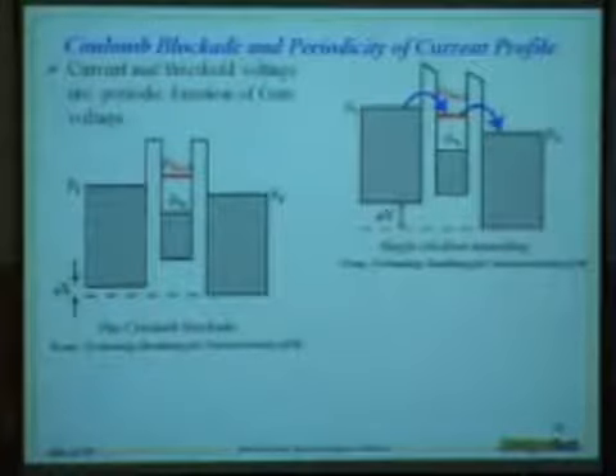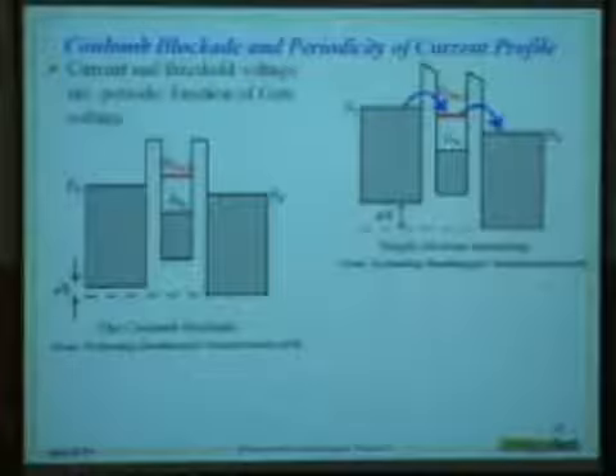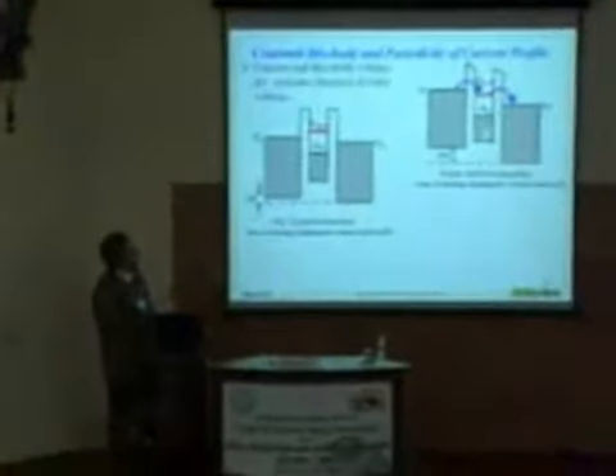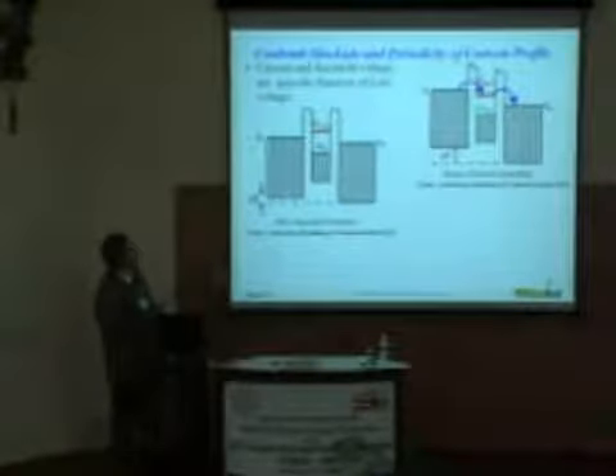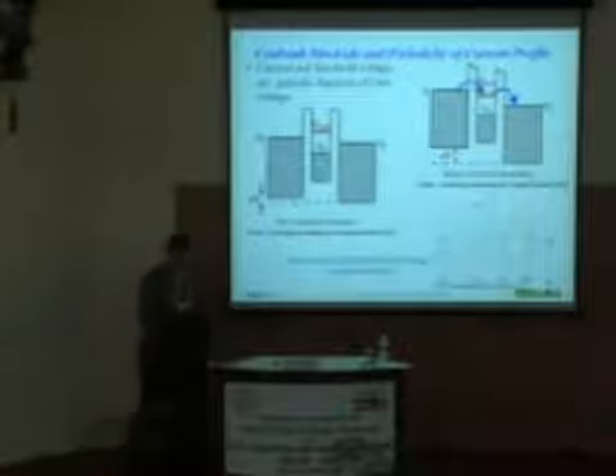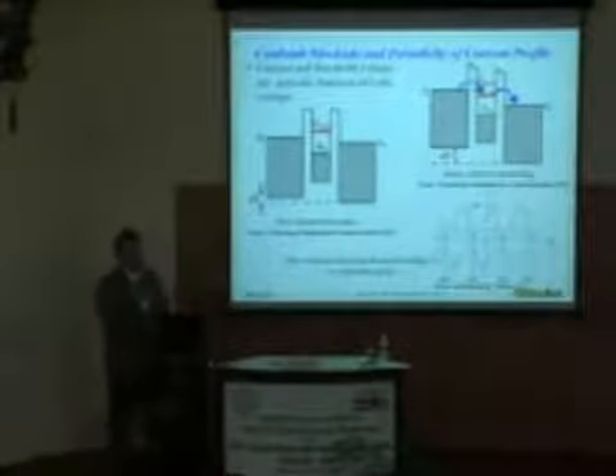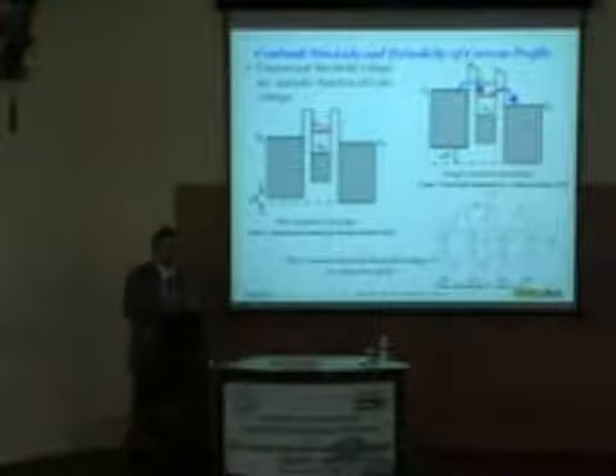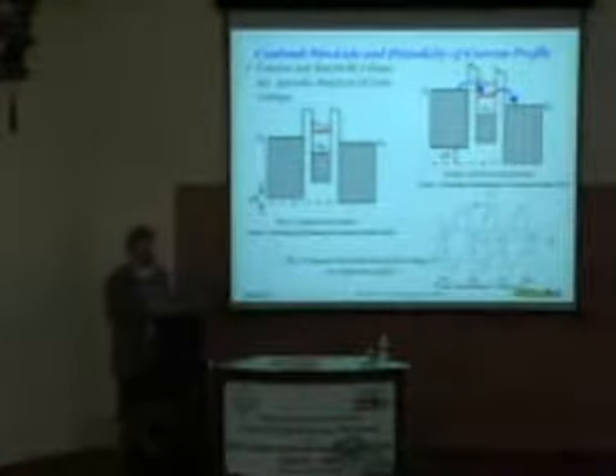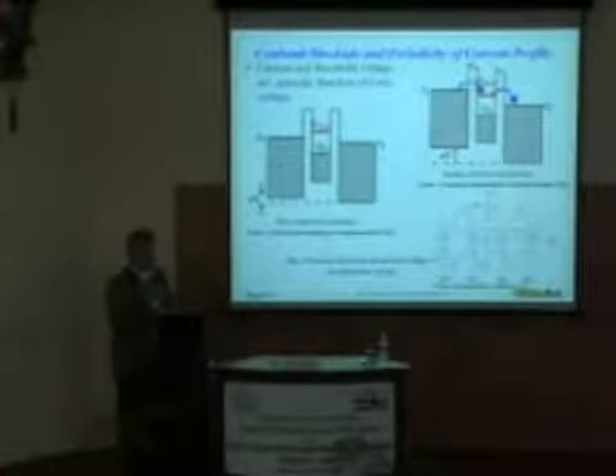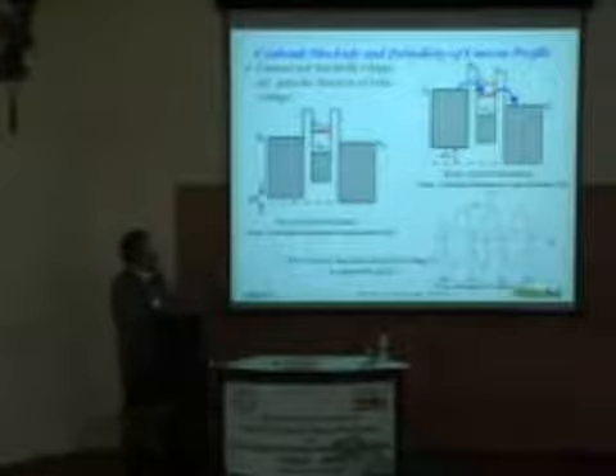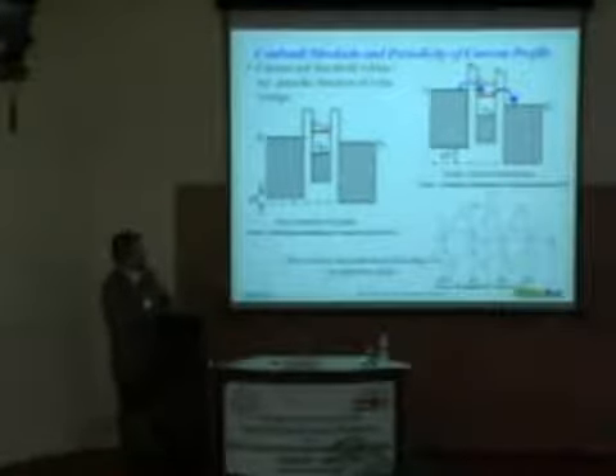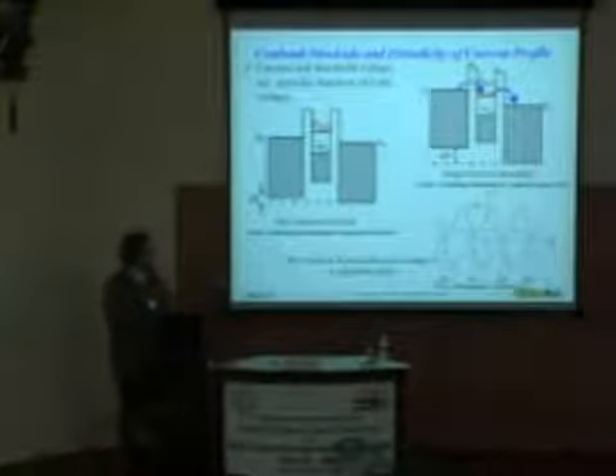So as I mentioned earlier, the favorability of tunneling depends upon the energetics of the conditions of the quantum dot with respect to the source and drain. And so the side gate or the gate electrode can change the potential on the quantum dot, allowing for a favorable transition to take place one way or the other way. These devices can be produced in a fashion where it's a very reversible device. The source and drain can be reversed, or it is possible to make them look very one-sided by adjusting either the width or the barrier height from one side to the other between the source and drain of the device.